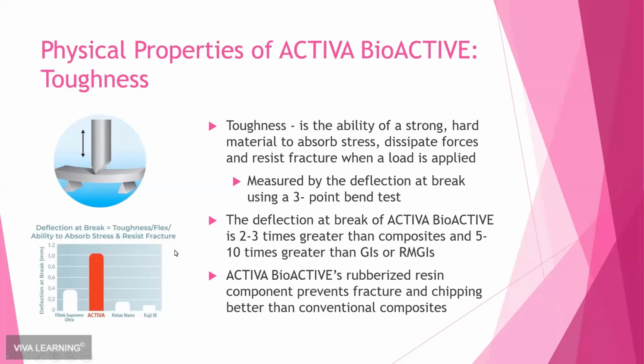So if you look at the graph on the left, you can see that the deflection at break, the toughness or the flex of the material of Activa Bioactive is superior in comparison to the Filtek Supreme Ultra, again, the Ketac Nano and the Fuji 9. This is due to the composition of the Activa Bioactive material. There is a rubberized component to this material that makes it so that you get more flex and less fracture. So when you're looking at this, to say that it's 2 to 3 times better than composites, 5 to 10 times greater than a glass ionomer or a resin modified glass ionomer, this is a material that's really intended to withstand a lot of force and prevent any sort of fracture or chipping within a patient's mouth.